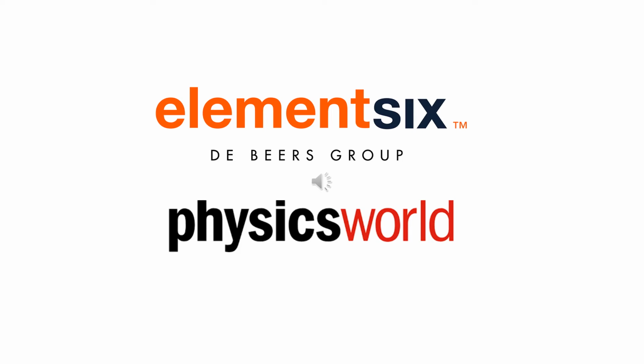The second is thermal vibrations. Crystal vibrations are another way that the environment interacts with quantum spins, quantum states. But because of diamond's mechanical properties, those stiff, short, tight bonds, the actual vibrational energy is such that it doesn't interact with spin. So again, you don't get phonon-driven decoherence mechanisms. And the last part, which the physicists will understand: spins can also interact with orbital motion via the spin-orbit interaction. Again, that in diamond is very, very small.